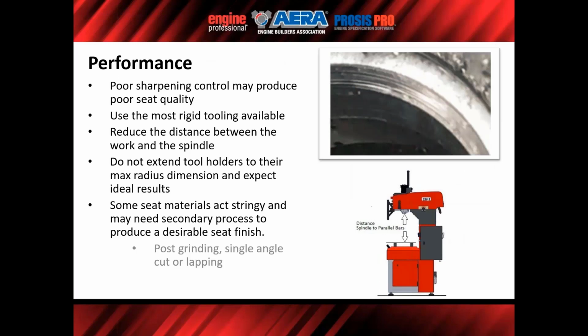So performance: poor sharpening can produce poor seat quality. Then there's the toughness of the material. There are seat alloys out there that have a lot of nickel in them, and much like the aluminum we were discussing earlier, that's a tough, stringy material, and what does it do? It bonds itself to that insert, but that tough, stringy material is also micro welding to the seat, and as you drag these chips in there, you leave channels in the seat. Now, when the valve is contacting it, you're only contacting the highest points. So again, do you need a secondary operation where you grind, lap, recut, or single angle cut? All things you need to consider.